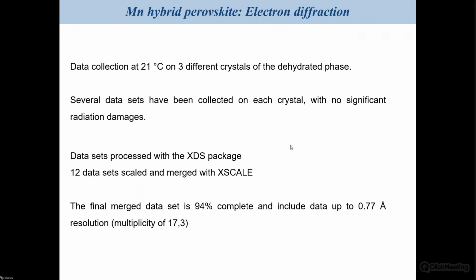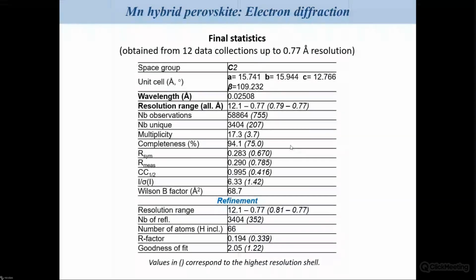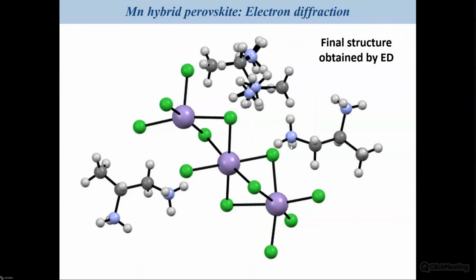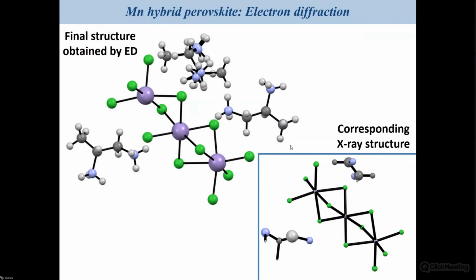At the end, they obtained 12 data sets that were merged together. And the final data give you very good completeness for a very good experimental resolution, which is very, very high for such kind of experiments. Here you can see more details about the data collection. And what is interesting is that using electron diffraction, you're able to have a very, very precise structure because they have been able to precisely define where the propanediammonium molecules are in the system, but they were also able to identify that you have a disorder for such kind of molecule, which is completely not possible with X-ray diffraction, because this is what you obtain. It's in line, but really, really more precise with electron diffraction.